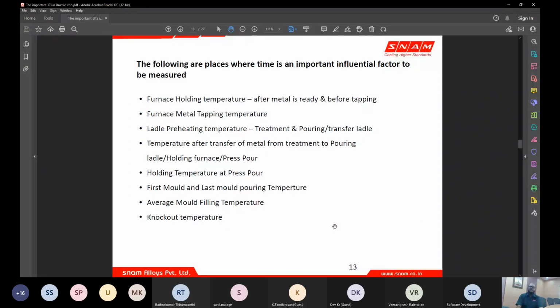And next comes the furnace tapping temperature, which is generally being measured. There are some shortcomings in foundries: when the metal level keeps going down in the melting furnace, people find it very difficult to measure the temperature. With their experience, they visually analyze the liquid metal's color and say it can be close to 1500, 1520. But every degree Celsius of temperature has an impact on your entire process of ductile iron production, because temperature has an effect on your ferrosilicon magnesium's dissolution and the recovery of magnesium. Your temperature loss is going to be determined by the temperature at which you tap.